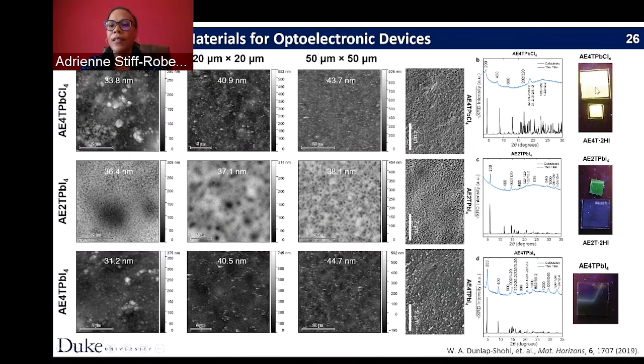And here we can see that in this film, you'd expect to have recombination across the organic. And in fact, that's what we see because we're comparing the luminescence from the perovskite to the luminescence of just the organic part, and it's the same. And in this material, we expect it to have recombination across the inorganic, which is what we see because we get this green color from the perovskite, but the blue color from the organic part. And that's because the recombination in this case is happening across the inorganic. And then for this material, we expect to see no recombination because it's a type 2 lineup. And in fact, it's what we see from the film, the suppression of luminescence.